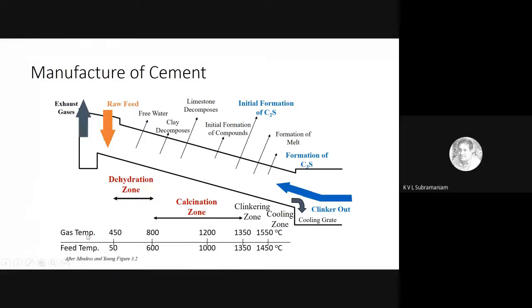If you look at the bottom here, I have a temperature chart. What enters the kiln at the raw feed is hot in itself. It is 450 degrees Celsius there. And at the exit stage, where I have the heat source, the temperature can go as high as 1600 degrees Celsius. So it's a very, very hot drum. And this drum rotates. As the raw feed is dropped into the drum, and as the drum is rotating slowly, the charge starts moving forward. And as it moves forward, the temperature in the drum is increasing as we go towards the open flame, or towards the bottom end of the drum. So as the charge is moving forward, it is being exposed to a higher and higher temperature. So what happens initially? Whatever free water was available in the system escapes.